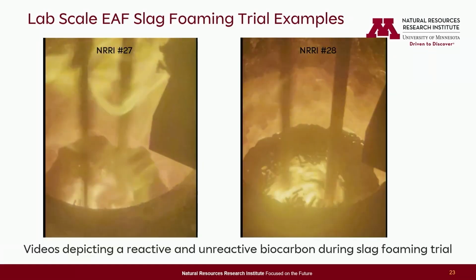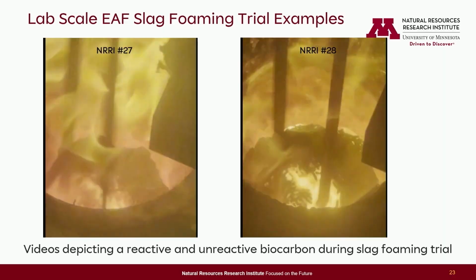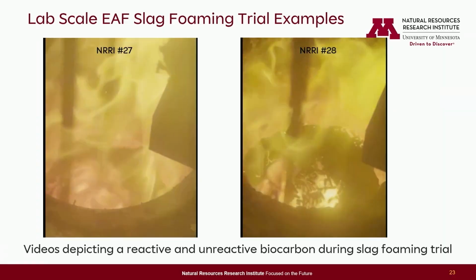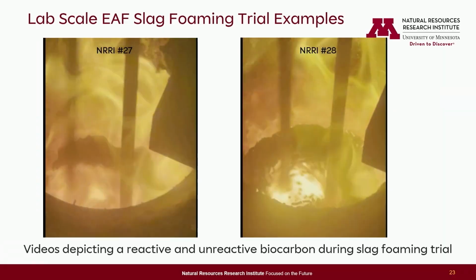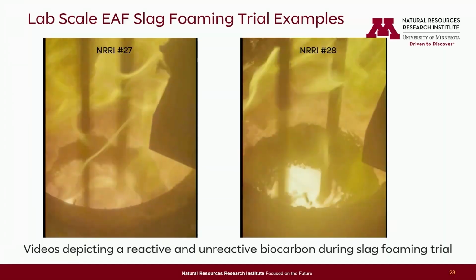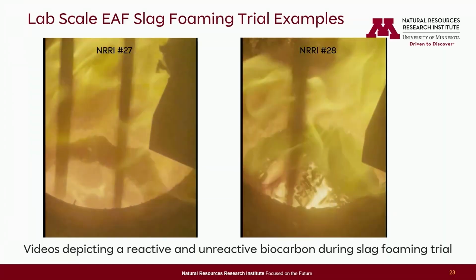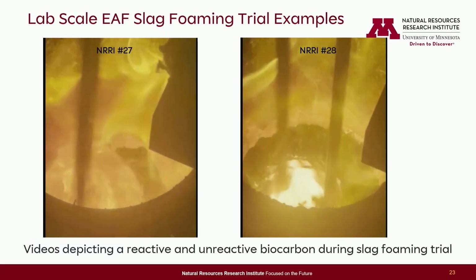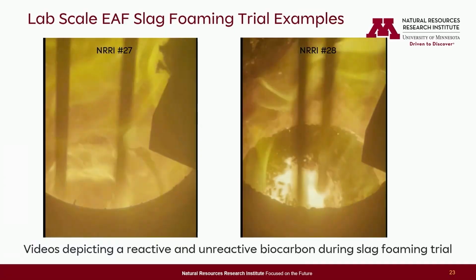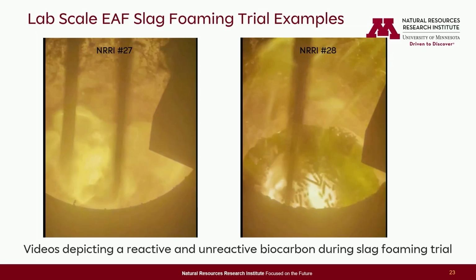So we try to keep everything the same. It took a long time to create this test. We played around with a lot of different parameters. And you can see the one on the left here is starting to foam. You can see the bubbly slag layer, and the one on the right is not reacting really at all. You can see even the pellet shape is not even changing.